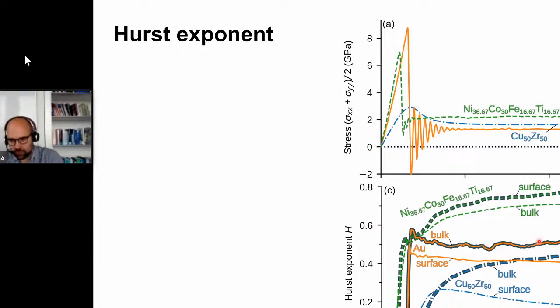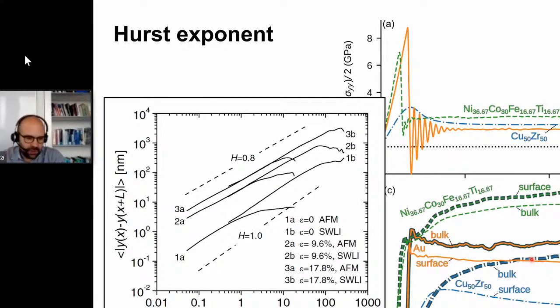The gold gives us almost 0.5, and I would like to illustrate to you why that is as a very simple explanation of what we are seeing here. And the copper zirconium is something that we are still working on that is actually highly temperature dependent. I don't have the data on these slides. Okay, just comparing to Michael Zaiser's work that I've shown before. So this was the scaling on potassium chloride and lithium fluoride. This is close to what we find actually for these multi-component alloys in our systems.